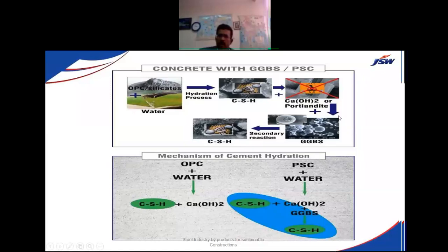Water penetration will happen. So this product once again reacts with GGBS, if you add slag or GGBS, and develops into additional calcium silicate hydrate gel through secondary reactions. So this will attack this calcium hydroxide and convert it into calcium silicate hydrate gel.